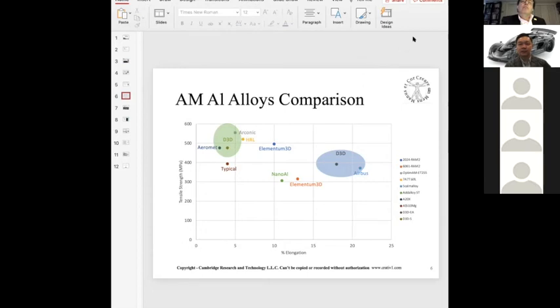That begs 2 questions, right? How fast can I control my laser? If I want to print fast, the first principle is to increase the laser speed and the recoating rate to get as much material deposited and sintered as possible. But that logic is really limited by how fast you can get the smoke away, or reduce the amount of spatter creation. So we are tackling this from a fundamental standpoint by changing the chemistry.